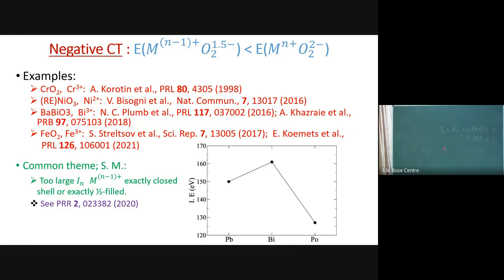If the ionization energy of n-1 to n+1 is large, those are the systems for which this will be greater than 0, and the system will be in the lower valence. So we are arriving at a criterion that has got nothing to do with copper oxides yet. Those systems in which the ionization energy of the lower charge is very high might be in a lower valence state. So what are those? We all do atomic physics at a certain point, when we are 20, and by the time we are 50, we have forgotten that. Maybe it comes back by the time you're 70.